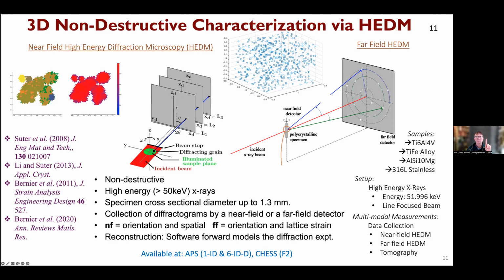And furthermore, you take that sample and you rotate it by a very small increment and you repeat. And you repeat and you repeat until you have this stack of diffractograms that contain overlapping diffraction patterns from all the grains illuminated in a given layer. So that's what the green circle is supposed to indicate. And I hope you will believe me that software exists to take all of that diffraction information and extract from that, basically through forward modeling, what is the grain structure? What's the orientation map in that illuminated region?